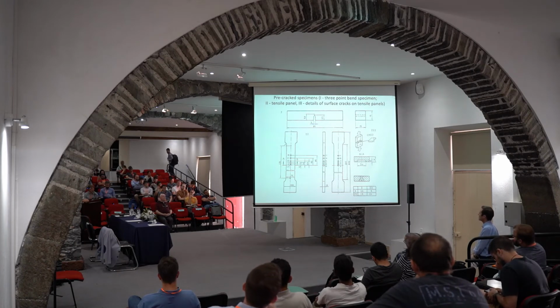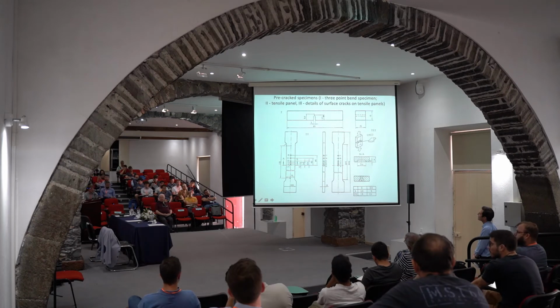Now just let me show you how JR curves were experimentally evaluated. At the top, you see 3-point bending specimens, and at the bottom, you can see tensile panels. It's very important that I explain now. We use this standard form of testing, but this is over-conservative for pressure vessels. Pressure vessels are in membrane stress state, and for them, tensile panels are surely more relevant, but they are not according to standard. So we did both.